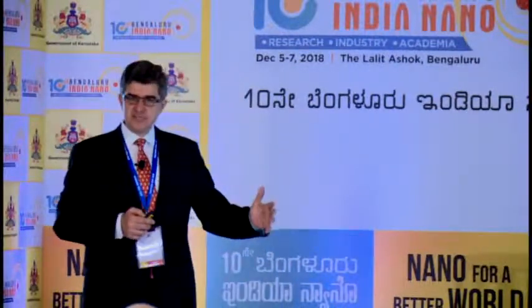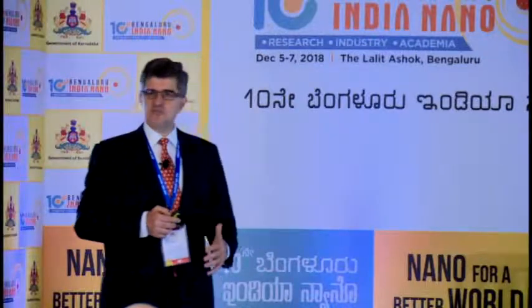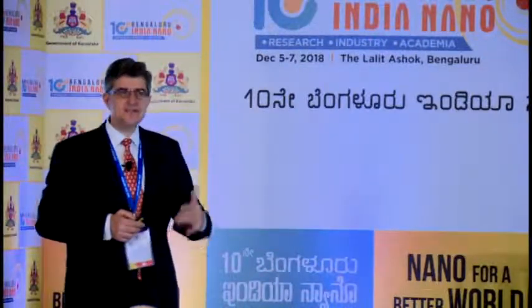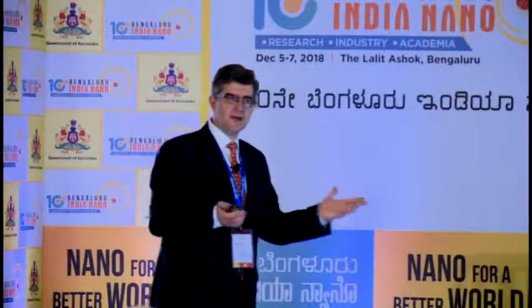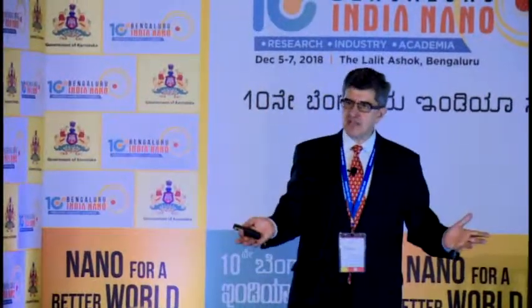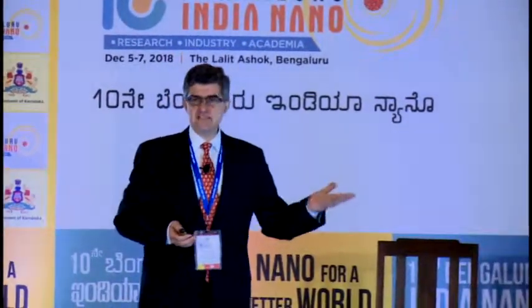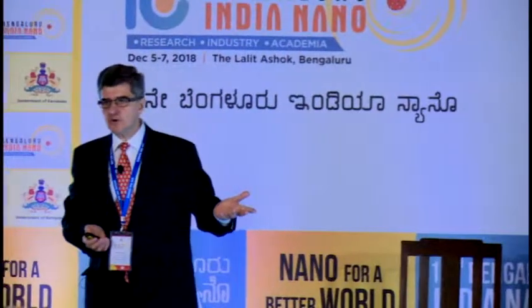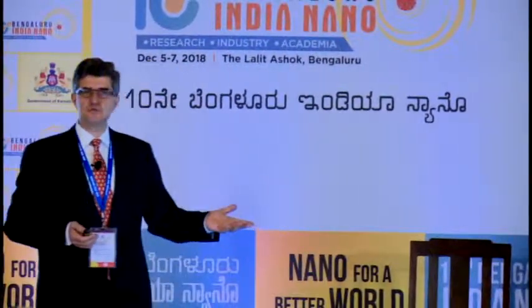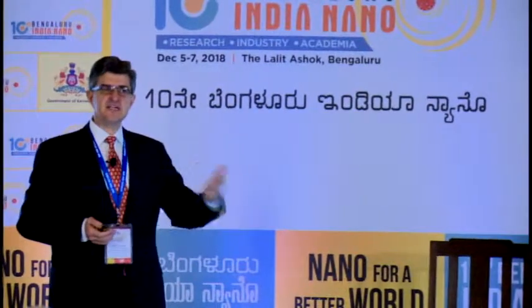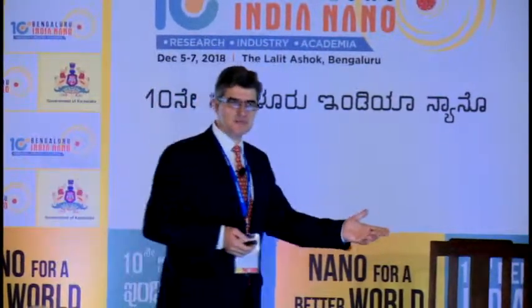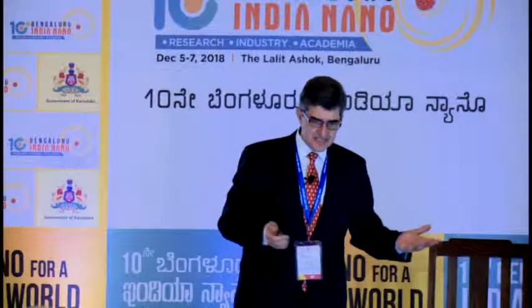But moreover, the surface of these materials looks like the surface of a transition metal oxide or hydroxide. And oxidation of the surface, unlike in graphene, does not kill conductivity. The material still remains a metal. So they combine the properties of real metals, real two-dimensional metals, while chemically on the surface they look like transition metal oxides. So they can be used, for example, to store energy in batteries and supercapacitors. They can change oxidation state. Many transition metals are good catalysts.